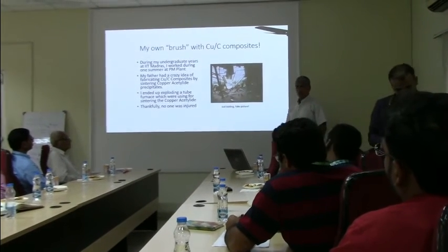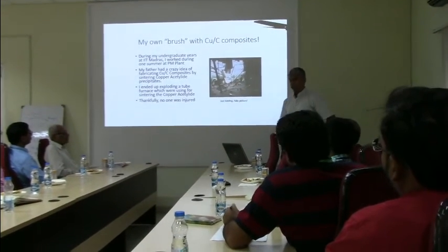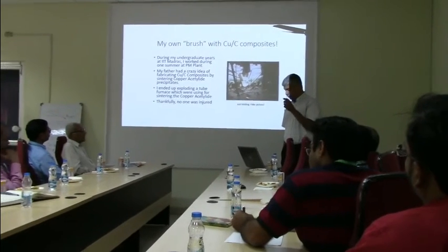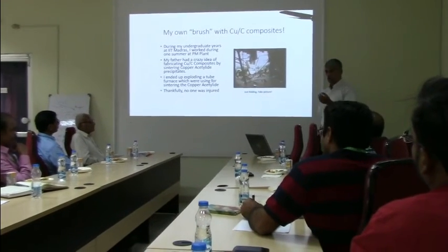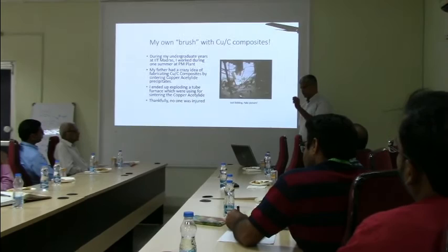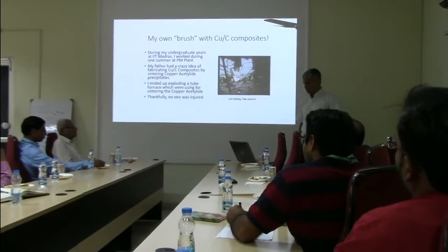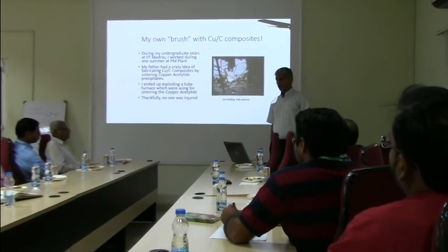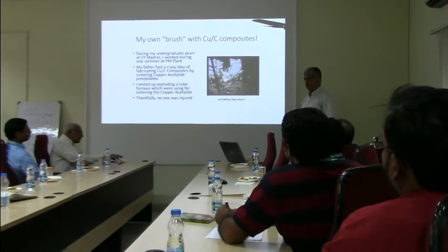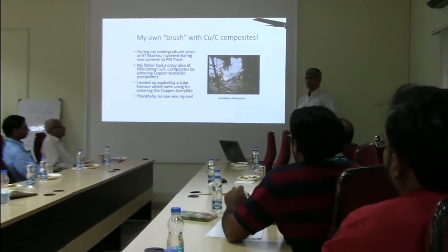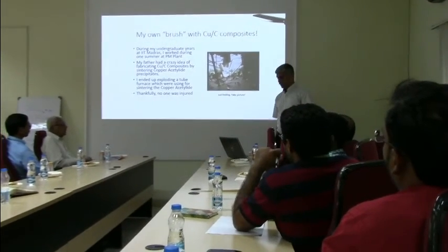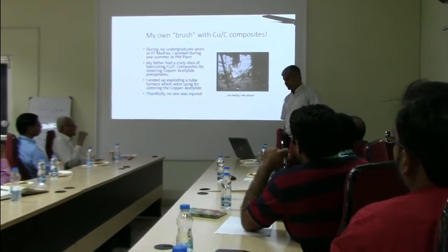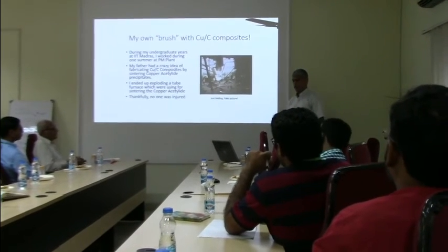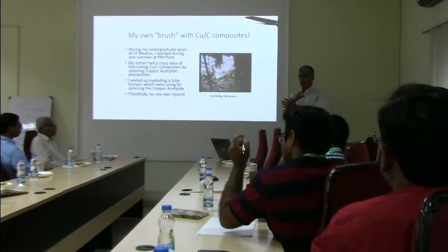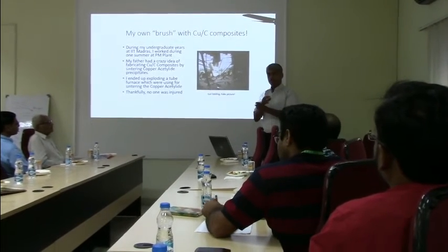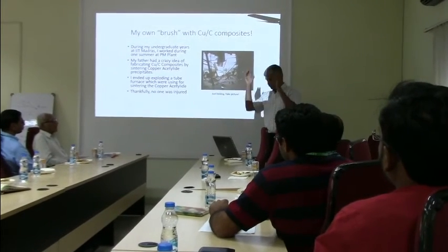There is a problem. The copper acetylide has what's called water of crystallization, the molecules of water attached to each molecule of the copper acetylide. So normally, if you don't dry it, if it's under moist conditions, it's very stable. But if you're trying to sinter it, you reform acetylene from this compound. And so that acetylene will catch fire and explode.